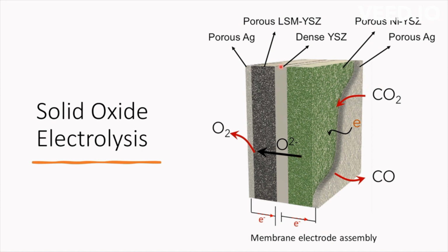So in a solid oxide device, the electrolyte is solid, which conducts the oxygen ions from one electrode to the other electrode, and this conduction takes place at pretty high temperature, around 800 degrees Celsius. So generally, the solid oxide devices are operated around 800 degrees Celsius. At one side of the electrolyte, cathode catalyst is coated, and on the other side, anode catalyst is coated.